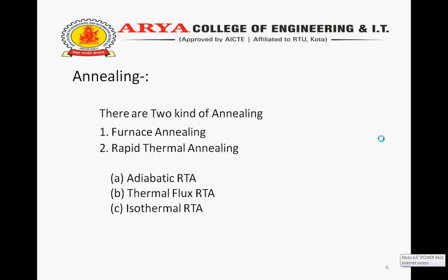The result of furnace annealing is a reduction in the fraction of active dopant. This is most pronounced around the peak of the dopant distribution where the damage is greatest. Second is rapid thermal annealing. Furnace annealing is capable of supplying high temperature, but the practical steps required to insert and remove wafers without stressing them take approximately 15 minutes. This is much longer than required to remove damage at high temperature and so allows unnecessary diffusion.